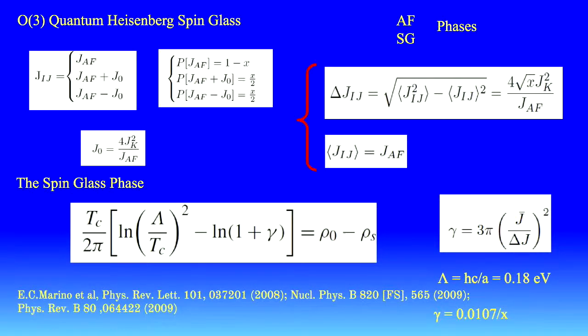Now the spin glass. If I take a Heisenberg quantum antiferromagnetic spin glass with these three possibilities of coupling constants with these probabilities, where x is the doping parameter, I get this variance and this average. So I have studied this spin glass largely in these three papers. This gamma has nothing to do with the previous. This was a gamma that I used in this spin glass. So I find this equation for the temperature separating the spin glass phase from the paramagnetic phase.